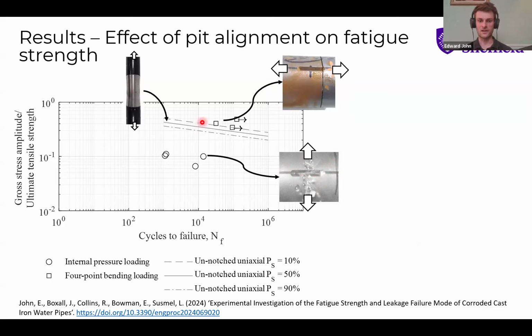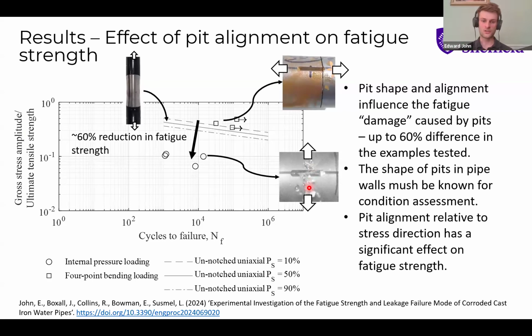And then this top data set here is the axial pit under bending loading. So that's creating a stress that acts parallel to the pit axis. And then the circles down here are the same specimen design, but subject to internal pressure fatigue loading. So that creates a stress that's rotated through 90 degrees and is perpendicular to the pit. And so even when we account for the fact that bending loading is less damaging than pressure loading, rotating the stress through 90 degrees so that it's perpendicular to the pit reduced the fatigue strength of the pipes by 60%.